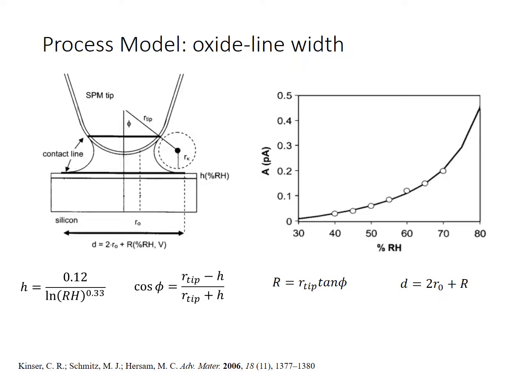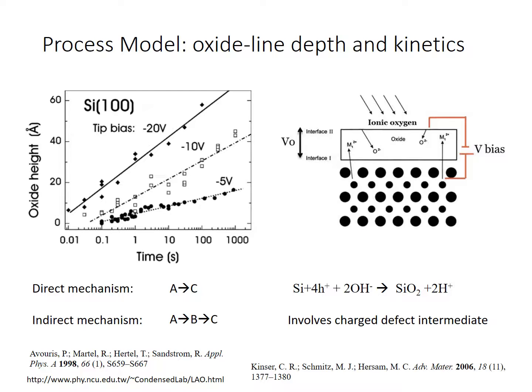The effective contact area is proportional to the relative humidity, indicated by RH, and the thickness of the water layer coating the sample. That's H, or the height of the water layer in the figure. First we have an empirical expression for H as a function of the relative humidity. It makes sense that the height of the water layer, and therefore the diameter of the meniscus, would depend on the relative humidity, since it's this layer of contamination that's being deposited onto the sample from the surrounding environment. Next we have a geometrical expression for the angle of the tip.